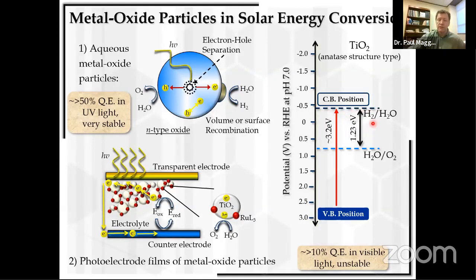that's dashed. And so you can see when light is absorbed and an electron is excited from the valence band to the conduction band, you can drive just barely water reduction in TiO2. And conversely, you can drive water oxidation by holes that are generated in the valence band down here, and they can be driven much more energetically. So for example, water oxidation, at least in the UV, can be driven at high rates with these large band gap semiconductors. And what my group has been looking at for the past many years is how do you lower this band gap